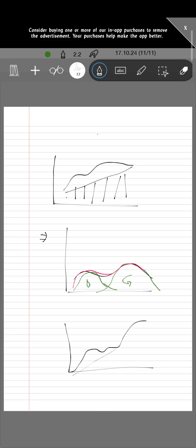This is the background correction. After fitting, we get three peaks: one small peak, and again this peak. This peak might reflect something else. This is the D, and this is the G. Sometimes there is a T peak, a tetrahedral peak, before the G peak. This is how the deconvolution is done.